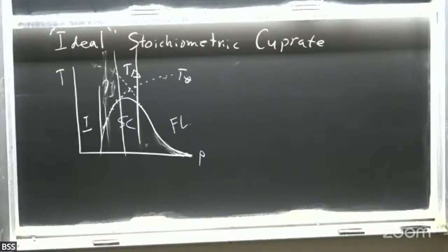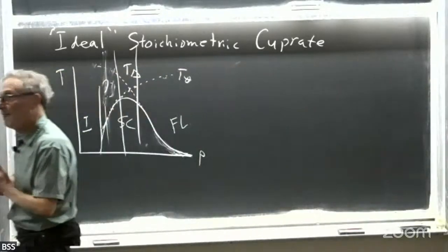There's 5 years ago, there's the demonstration that you could, with pressure, take YBCO oxygen 7 and tune it through the whole phase diagram. This was done by the Cambridge group. The only thing they have is Tc versus pressure. This is a stoichiometric compound. There's experimental evidence that it's much, much cleaner than anything else. The NQR line width is more than an order of magnitude narrower than in anything else. And this possibility has been dangling around for 5 years, and nobody has measured the superfluid density or killed superconductivity with a field and see if it has a strange metal. It's in my opinion, the most important open experiment in the field. Yes?